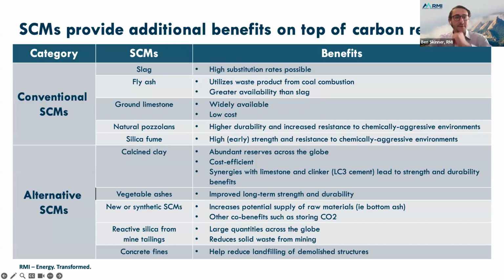To speak to some of the benefits that Sabbie already mentioned on the SCMs front, it's really important to note that while there often are some compromises as far as early strength or differences in workability, there are a lot of benefits to using SCMs in addition to the carbon reductions. For example, natural pozzolans have great durability and increased resistance to chemically aggressive environments. Similarly, calcined clays also have really good strength and durability benefits and perform really well in environments that have sulfates. Vegetable ashes are another emerging SCM that can show improved long-term strength and durability. And lastly, I'll mention concrete fines, which has that great circularity aspect that helps reduce landfilling of demolished structures.